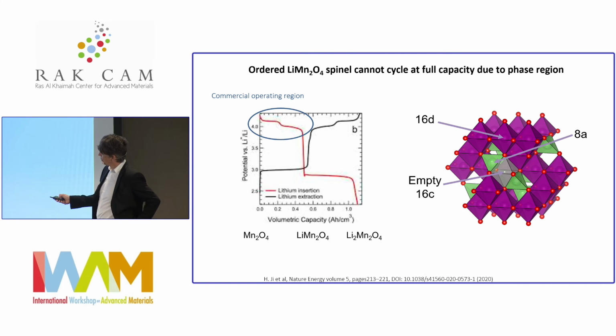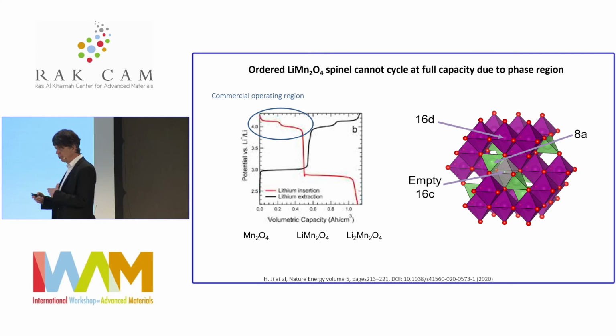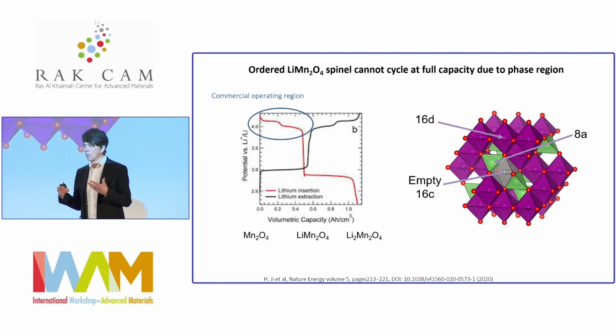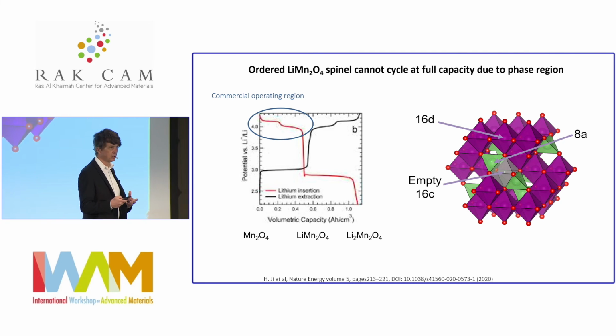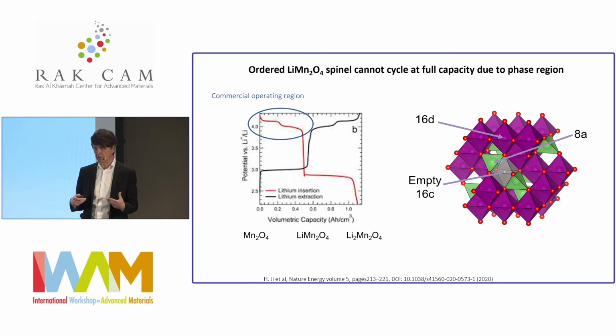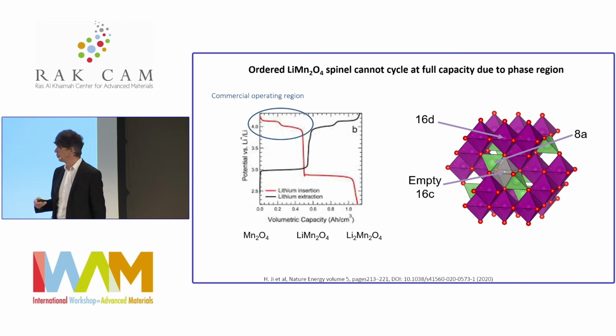But there's actually a whole lot of extra capacity sitting here, which you can reach by inserting lithium from LiMn2O4 to Li2Mn2O4. The reason this is not used in industry is because this is a first-order transition. This is actually a two-phase reaction, which is why the voltage is flat. And a two-phase reaction, by definition, is inhomogeneous in the way it occurs. So that means it causes stress and strain in the material, and it fractures the particles in situ.